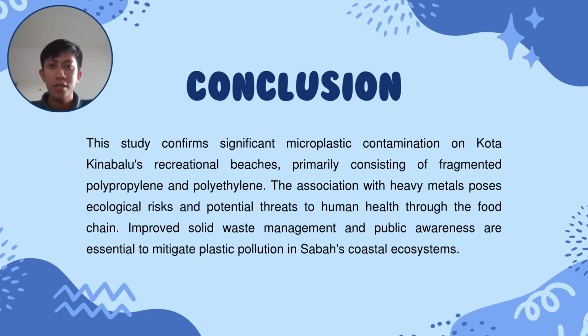In conclusion, this study confirms that microplastic contamination is present in recreational beaches in Kota Kinabalu and demonstrates that these pollutants are not only widespread but may also pose environmental concern. The results show that polypropylene and polyethylene were the dominant polymer types, mainly appearing as fragment particles, which suggests that larger plastic materials are breaking down into smaller particles over time.